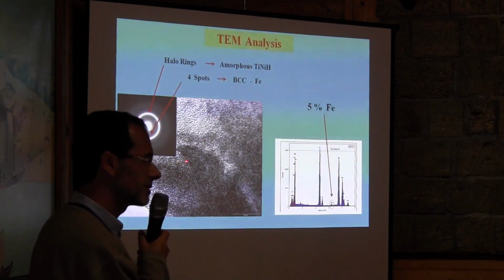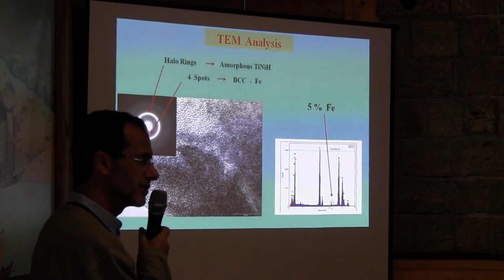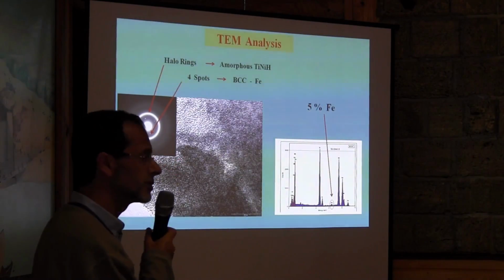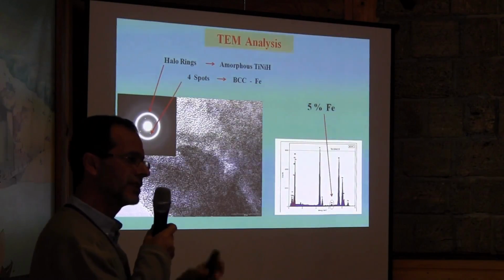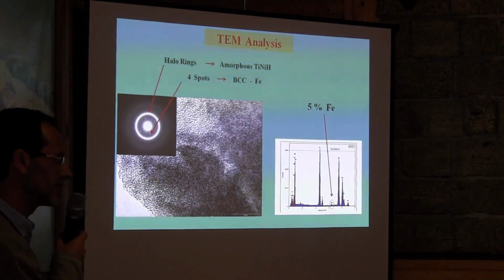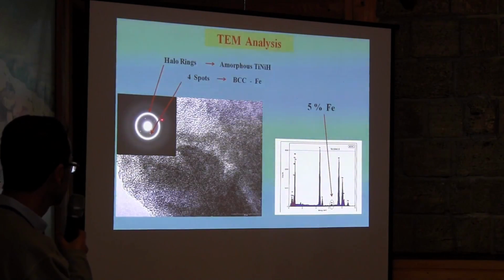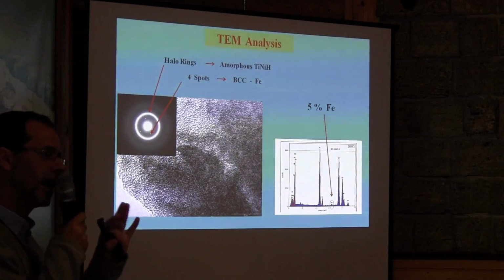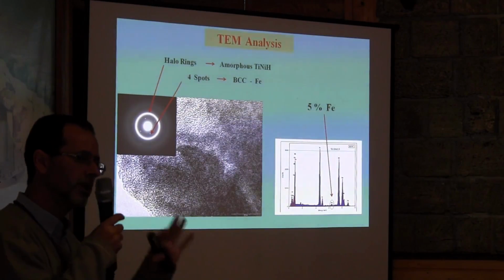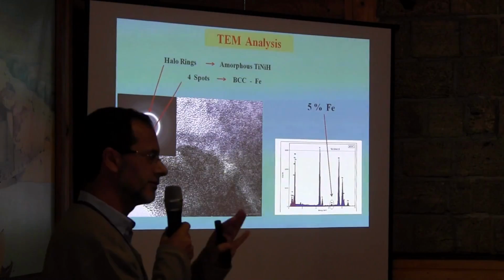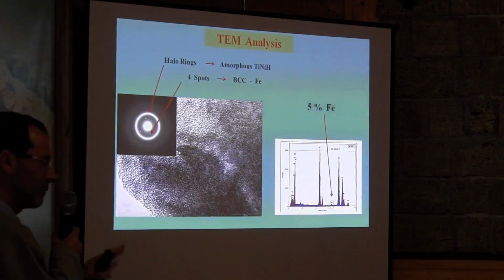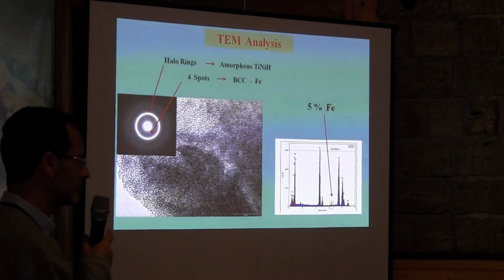What are the 4 spots? So you need to be very careful. The 4 spots belong to iron because it's contamination from the milling tools. So we have very nanocrystalline iron, and we can detect it with EDS, and amorphous. So we have amorphous matrix of nickel titanium with nano clusters of iron on the surface of nickel titanium, which is very useful for us.